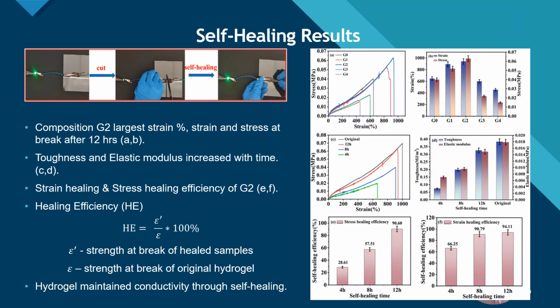After completing the tensile and adhesive strength testing, we moved on to self-healing. This was done by taking a composite sample of each of our samples, slicing them in half, and then dyeing the samples and putting the samples back in physical contact, allowing the complex group of intramolecular forces to slowly recombine into the polymers. These were allowed to occur over 12 hours, and then we sampled a similar tensile stress to break for all of the samples listed here. We found that G2 had the greatest total break stress and strain after 12 hours. Therefore, we selected G2 to investigate over a 12-hour period.